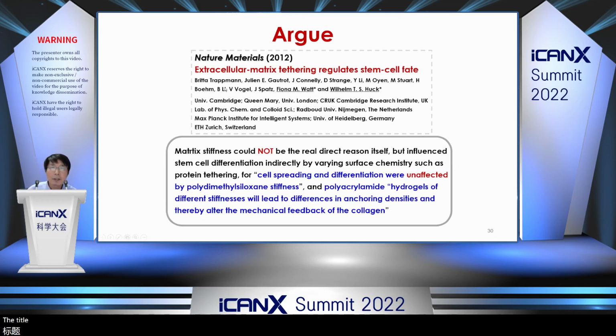The title is Extracellular Matrix Tethering Regulates Stem Cell Fate. So here is a sentence in their paper: cell spreading and differentiation are unaffected by matrix stiffness. So they think that the so-called stiffness effect arises because when the Discher group changed the stiffness, they also changed the surface chemistry. And the different surface chemistry led to different protein adsorption from the serum in cell culture. So that's the real reason.